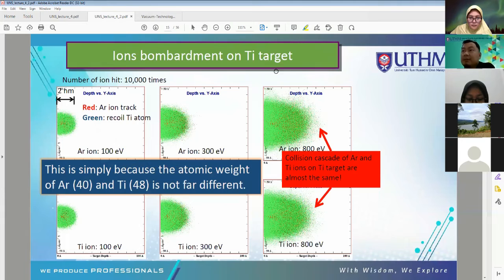Okay, so this is an example of how the ion bombards the titanium target. The ion will bombard from the left to the right, so it will penetrate inside the titanium material. For example, when you have an argon ion at 100 eV, this is the argon ion track in red, and the green is the titanium atom. You can see the argon ion will hit and penetrate inside the titanium. When we increase the argon ion energy, we can see the argon ion go even deeper.